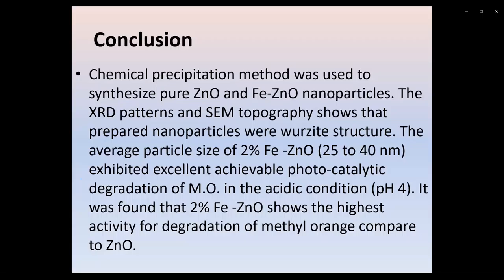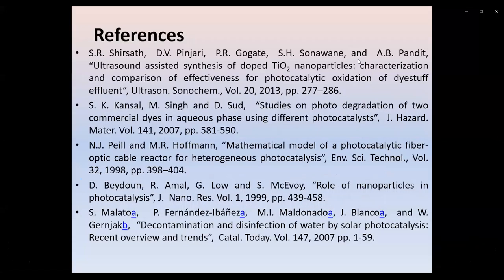The chemical precipitation method was used to prepare the pure ZnO and FeZnO nanoparticles. The XRD pattern and SEM topography show that the prepared nanoparticles have a wurtzite structure. The average particle size of 25 to 40 nanometers exhibited excellent photocatalytic degradation of methyl orange in the acidic condition of pH equal to 4. It was found that 2% FeZnO shows the highest activity for degradation of methyl orange compared to ZnO. The following are the references I made for my work. Thank you.